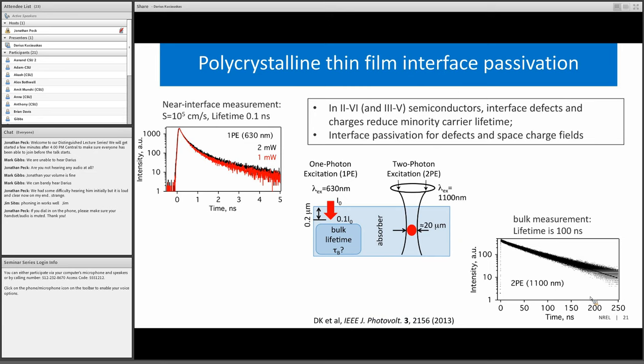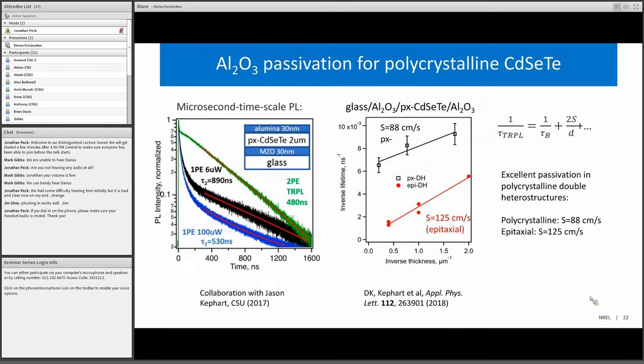The most successful passivation that is available today for thin films for cadmium telluride is by using alumina. So this research was started with Jason Kephart when he was working at Colorado State University, and the graph on the left shows the lifetimes, which are measured for only 2 micron thick cadmium selenium telluride film. These lifetimes are close to a microsecond. The time scale of luminescence here exceeds 1 microsecond.